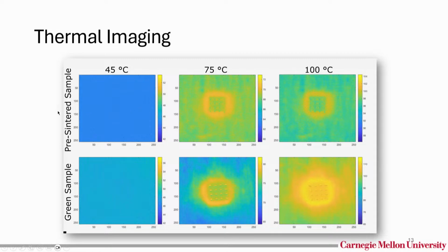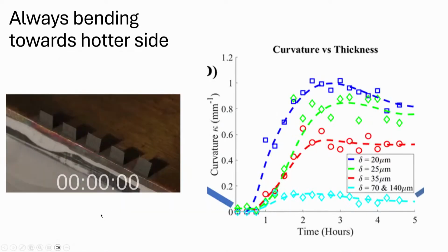Why is that? That's a whole other story. It has to do with how the thing is heated. It's very difficult to control temperature precisely, but there is a significant temperature difference between the outside of this array and the inside until the last stage. To make things simpler, we tried that with walls of different thickness,